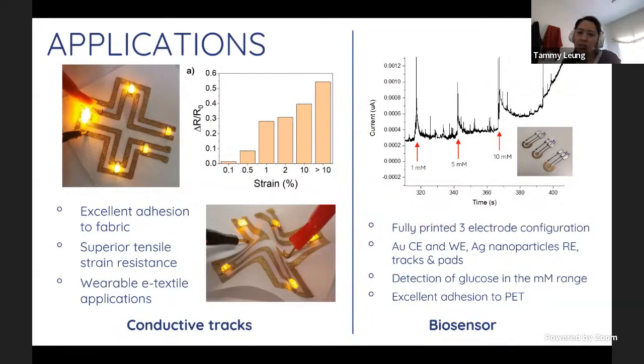Another application we had here is the development of a fully inkjet printed glucose biosensor. This biosensor consisted of a 3-electrode configuration where the gold was used as the counter and working electrode, and the rest, such as the conductive tracks, pads, and the reference electrode, were printed with the silver nanoparticles. However, due to the limited working area, glucose detection was only found in the millimolar range, which is appropriate for blood glucose detection in particular. Sensors that are typically printed with nanoparticles tend to have poor adhesion and often need an adhesion layer. Compared to those, in our specific sensors there was no delamination of the gold film seen, making it a potential candidate to be used as a reliable, flexible device.